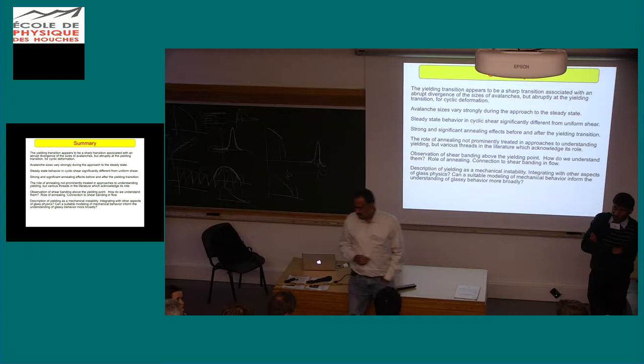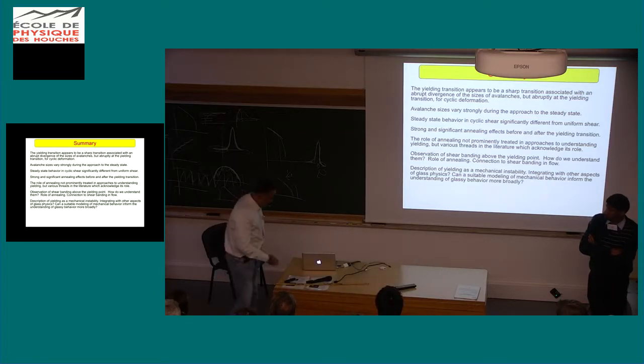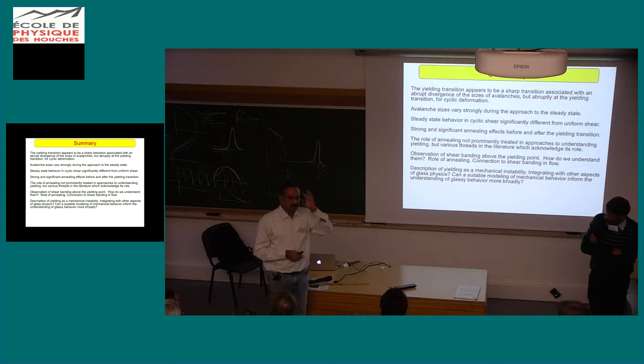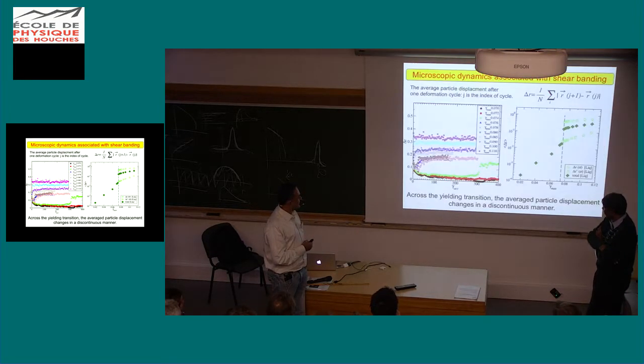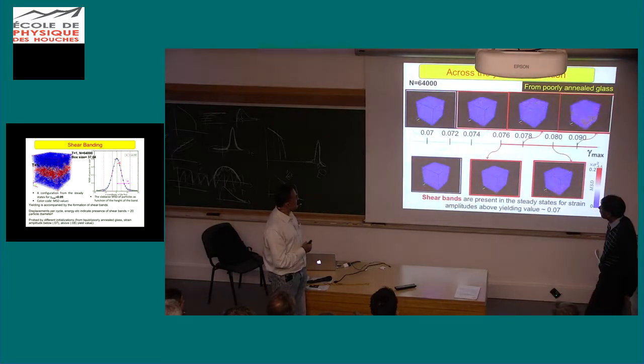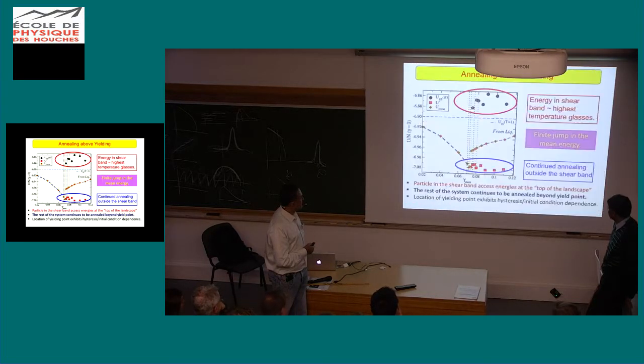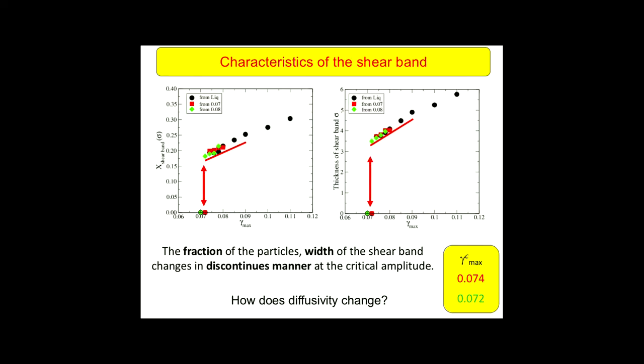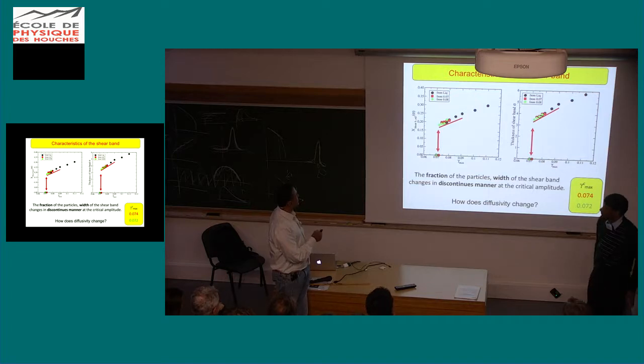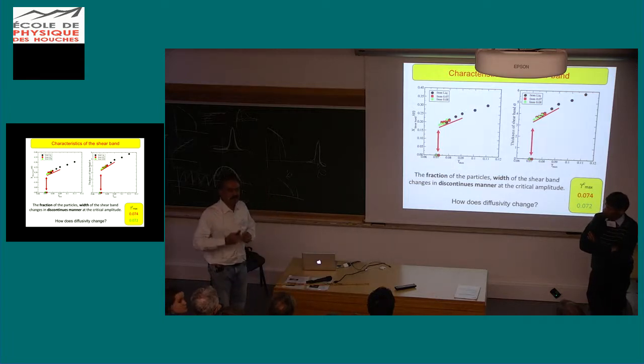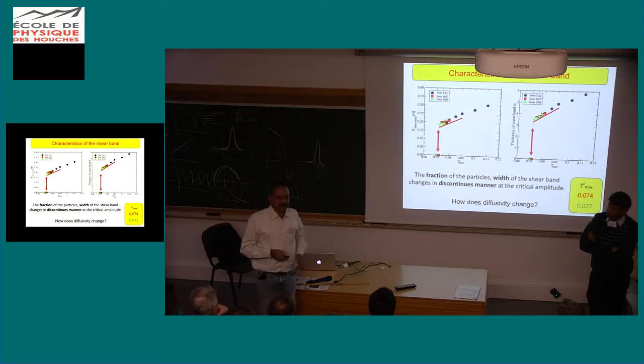Sure. Okay, so I don't know if it's direct, but you're right, the first part is the number of events, the number of regions that plastically deform during a cycle, go lower and lower, approaching zero, I suppose. But when the system yields, the fraction of the system that takes part in this is substantial for this size of simulations. So the number of particles in the shear band jumps from 0 to 20% of the system. So I don't know if there's a gradual change of activity that prompts these regions to form. What you have is a sudden emergence of a shear band.